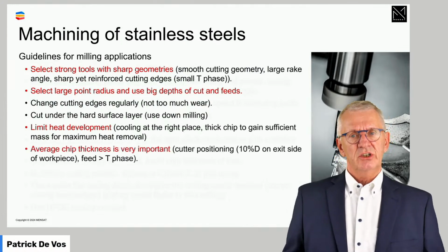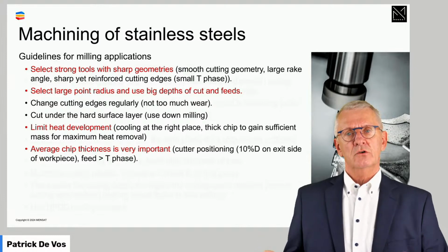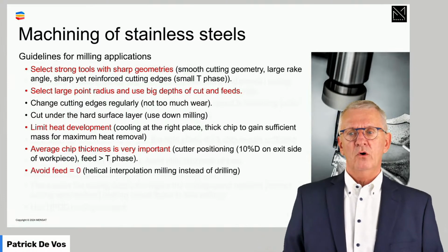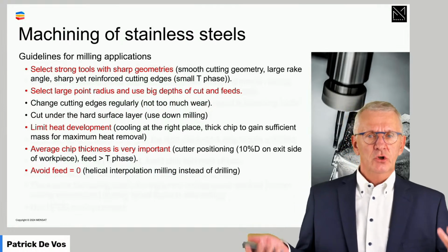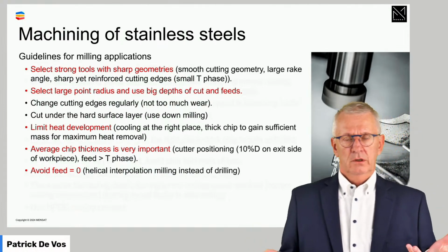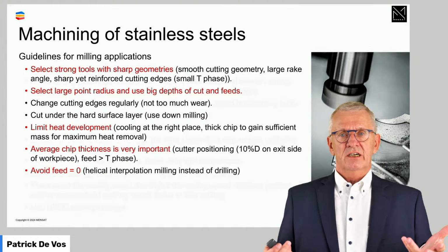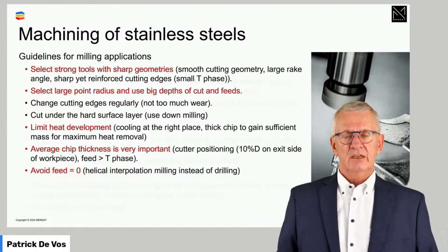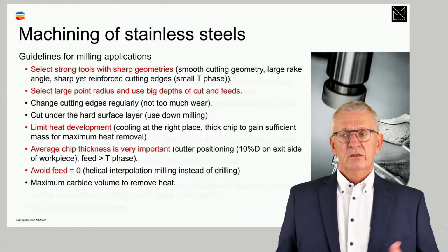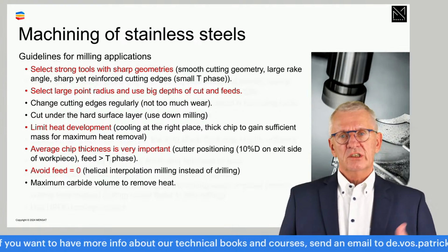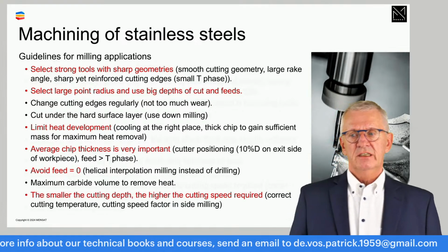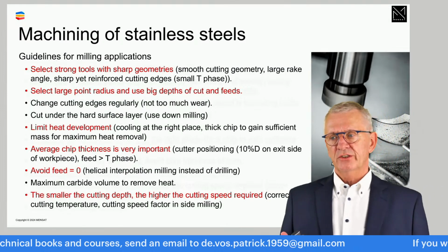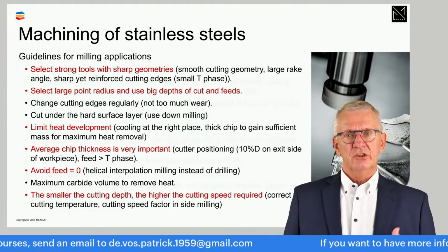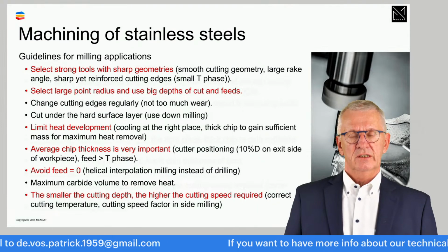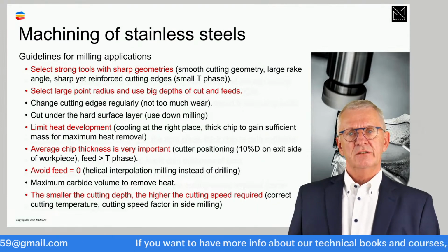Average chip thickness. Chip thickness is in general important. The so-called average chip thickness in milling is even more important. Avoid feeds near zero, because then you have strain hardening extremely taking place. Use maximum volumes, carbide volumes to evacuate the heat. And also here, small depths of cut means high cutting speeds. The so-called speed factor in milling applications is a very important thing when you machine stainless steels.